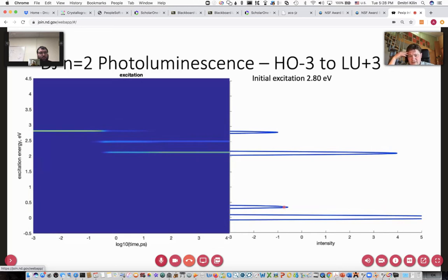And if this goes through the radiative pathway, it may give rise to this infrared peak at 0.3 electron volts that David is pointing to with the laser pointer right now. Would it be a good hypothetical interpretation? That makes sense to me.